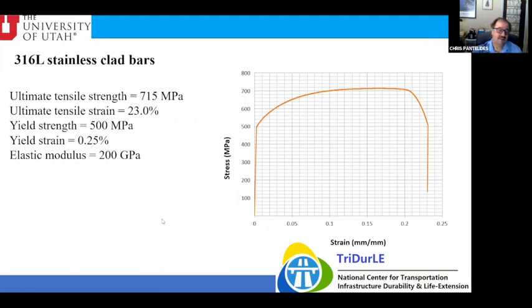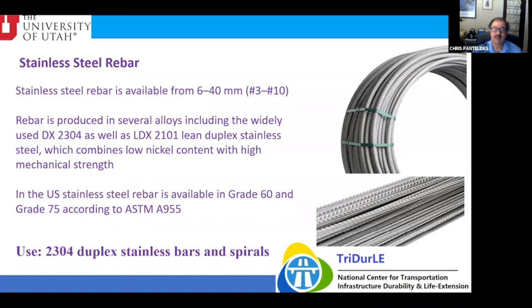So we tested these stainless clad bars: ultimate tensile strength 715 megapascal. Ultimate tensile strain, though, unlike the fiberglass bar, is 23%. This one has a yield strength of 500 megapascal at a yield strain of 0.25%. Elastic modulus is 200 gigapascal. So it's definitely a ductile bar.